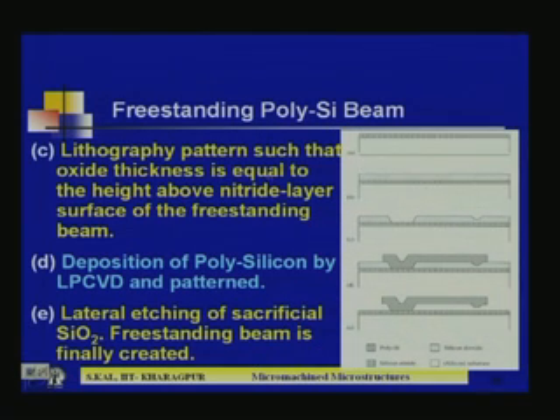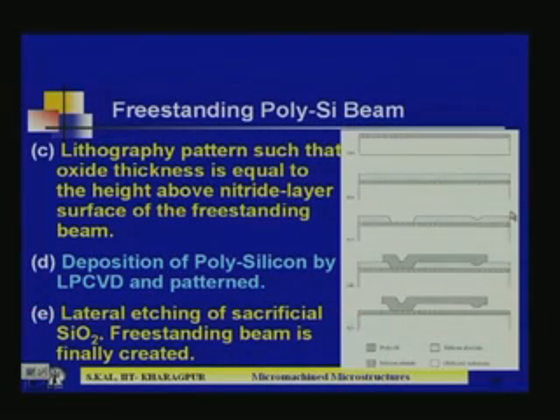lithography pattern such that the oxide thickness is equal to the height above nitride layer surface of the freestanding beam. So, now this is lithography pattern, deposition of polysilicon by LPCVD. This is the bottom, was the nitride, you can see nitride, then this is silicon dioxide, then you are getting this polysilicon.